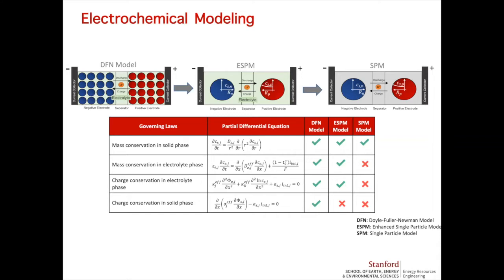There is an assumption made there, which is that the particles are spherical, which is a good approximation for certain chemistries like NMC, but it's not a good approximation for LFP, which on the other hand has a more squarish type of particle shape. We can simplify the complexity of the DFN model by neglecting the charge conservation in the solid phase. And within this framework, we assume that the particle is spherical. There's only one particle in each electrode.